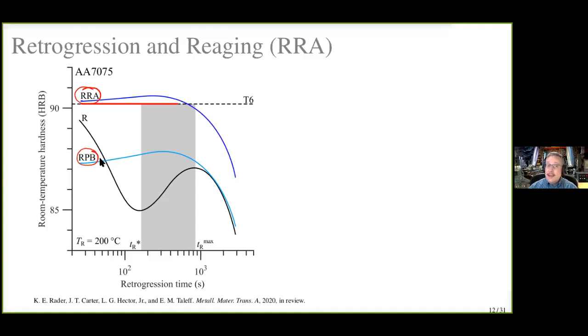So it would be nice if the paint bake would serve as the reaging heat treatment. And it does somewhat. So you'll see here that we do gain some strength back from applying the paint bake instead of the full reaging, but the full reaging heat treatment is more effective. Okay. The paint bake would be nice to use because it's already in the automobile assembly line and you get to use that for free. So just not quite as effective as the full reaging for 7075.